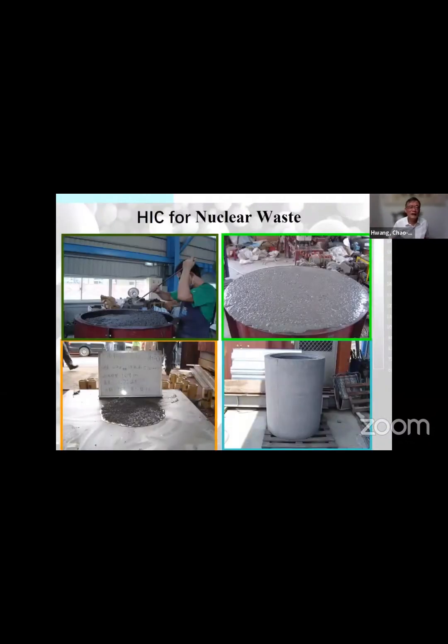And for the high integrity container for nuclear waste, you will see that we made this concrete. Its high strength is 17,000 PSI. We use water about 120, a very, very small amount of water because we try to reduce shrinkage. And we add a large amount of steel fiber. So the concrete looks like this outside. They put the waste into the container and cover it. Then we can keep that for more than 300 years. Next, please.